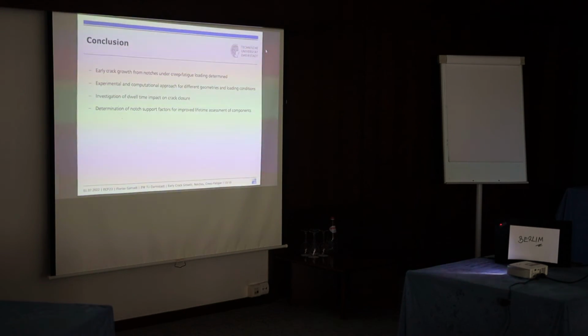Of course, there are other time-dependent effects which act on crack closure. This was what we observed for low-alloyed steel. Their oxidation-induced crack closure is as well very important. Couldn't talk about this today, but we've seen this. And in the end, using the notch support factors, you can definitely improve your lifetime assessment of your component.